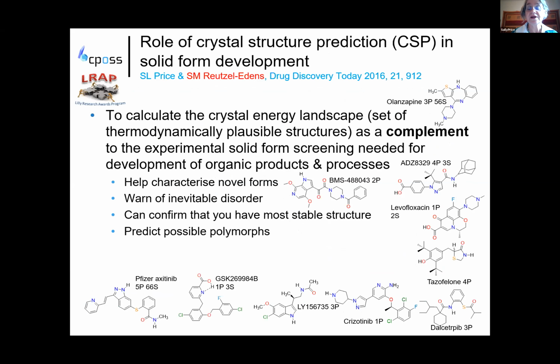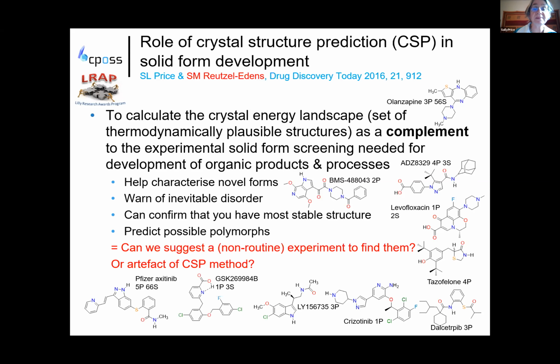So we wrote this survey of studies that had been published, done in conjunction with industrial pharmaceutical labs, and you get some sense from the names of using crystal structure prediction to help with their polymorph screening, characterizing forms, looking for disorder, as well as trying to confirm that they had the most stable structure and predicting possible polymorphs. But this over-prediction means that there's a huge question of which of these structures are artifacts of the crystal structure prediction method, particularly neglect of temperature, and I'm working with Matteo Salvalaglio on this, or are they undiscovered polymorphs, and can we suggest a non-routine experiment to find them?